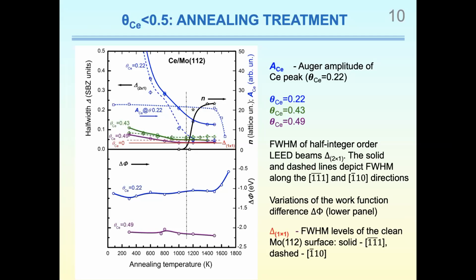No substantial changes in amplitude and work function difference are seen until the start of desorption. We see that it's quite stable here and here. Therefore, annealing at temperature from 300 to 1400 Kelvin causes no changes in the coverage degree. The earliest manifestation of annealing effect on the order in cerium films is revealed in sharpening of half-integer LEED spots. The main ordering in the primitive 2x1 lattice occurs within the interval from 500 to 1000 Kelvin.